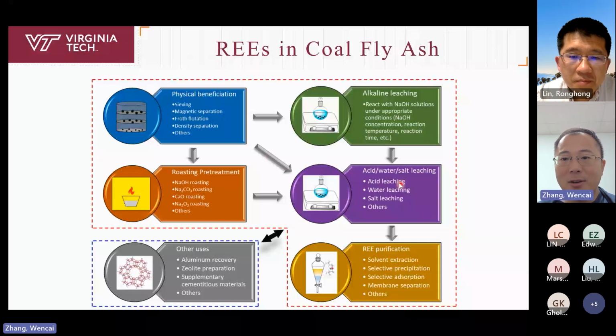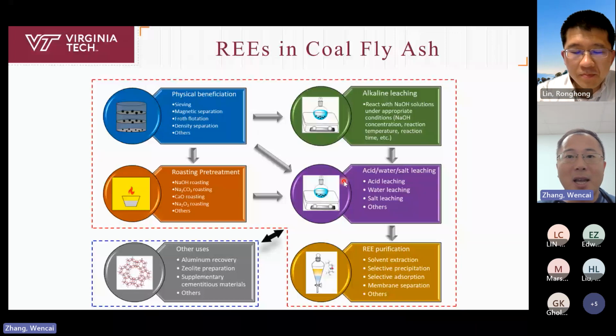And once the rare earths are dissolved into a solution, you can do rare earth purification. There are many different ways you can do rare earth purification. For example, solvent extraction, selective precipitation, selective adsorption, membrane separation, and some other separation technologies can also be used. So in this process, you can achieve the recovery of rare earths from coal fly ash. But as I mentioned, in coal fly ash there is only around 500 ppm, which is 500 milligram per kilogram of rare earths in coal fly ash.